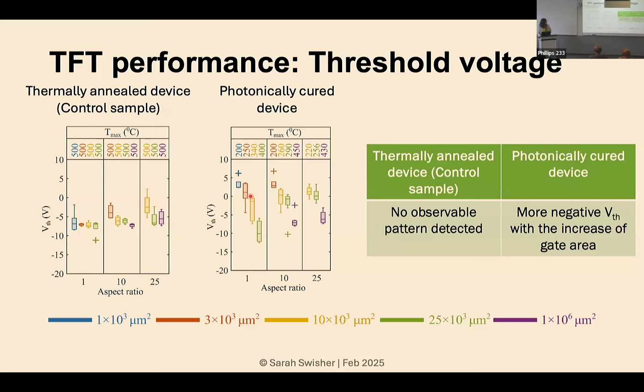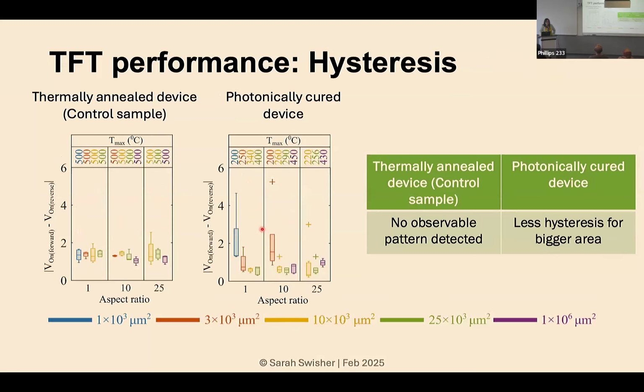And we see something similar for the threshold voltage, which is also expected when you increase the curing temperature of indium zinc oxide. You tend to see a more negative threshold voltage. That's because you have a higher concentration of oxygen vacancies that are formed, and it's harder to turn these devices off. So your threshold voltage gets more negative. So again, the trend that we see here is very consistent with the temperature that we simulated. In the hysteresis, we see the same thing as well. The hysteresis decreases as we get to those higher temperature curing devices.